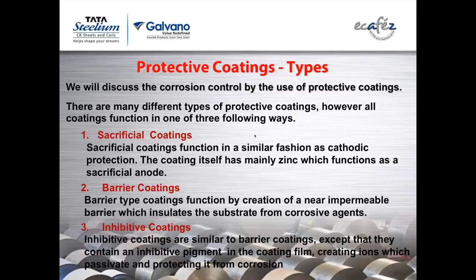Now, coming to protective coatings, there are three types of coatings which are usually used. First, we call it a sacrificial coating. The sacrificial coating functions in a similar fashion as cathodic protection. This coating itself has mainly zinc, which functions as a sacrificial anode. So sometimes we mix this zinc powder in the primers, or if I need some more corrosion resistance, I can spray it, what we call zinc metallizing, and then apply the next coats.